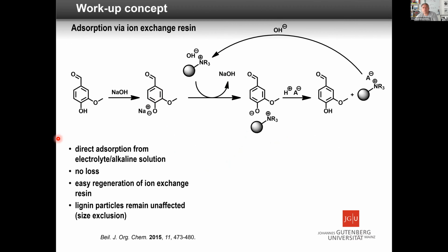And the point how this works is very simple. We use an ion exchange resin. That means you have the vanillin. This is deprotonated under these conditions. Then you have vanillate, and this sticks to the resin here, and it cannot be rinsed off by caustic soda because there's a strong interaction. I will come to that in a second. And then you have to neutralize this one here. Then this pops off, and you regenerate the resin once more.